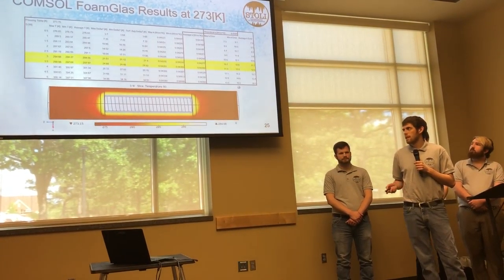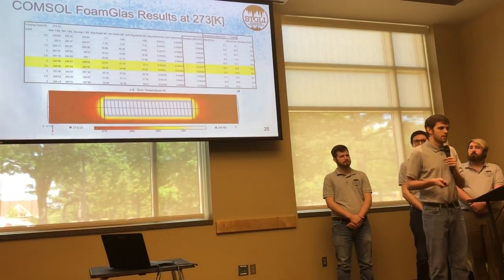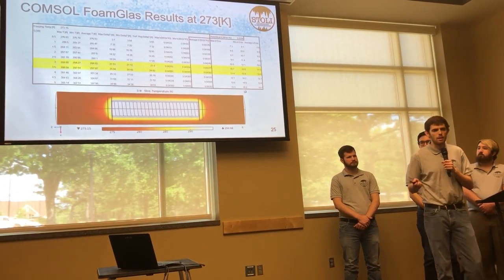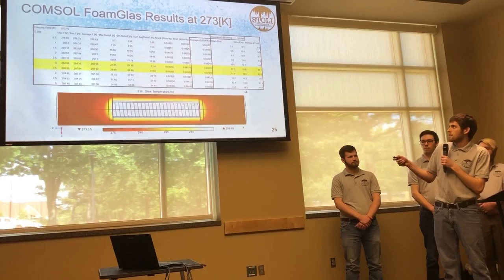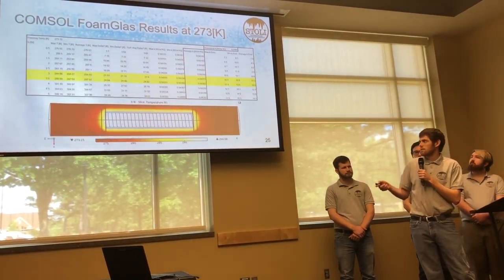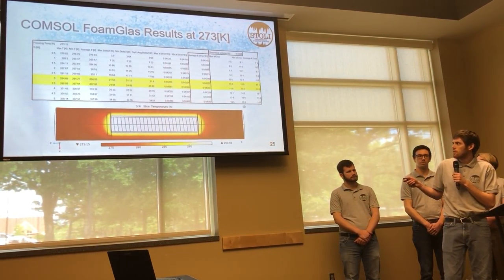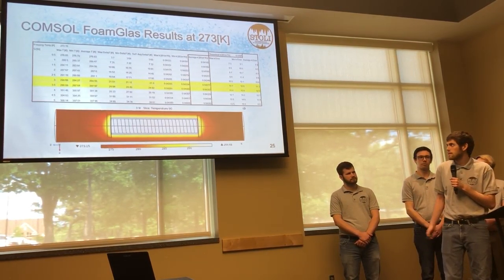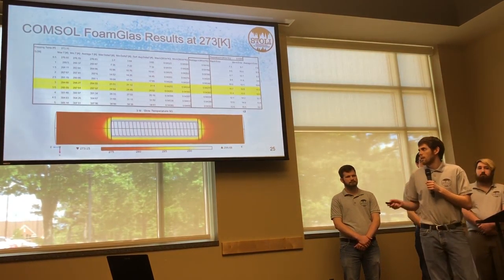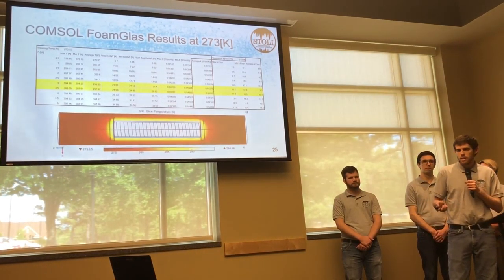Here is some COMSOL data. For our experimental tests we had a power input of about 3.25 watts. With our COMSOL results for foam glass at zero degrees Celsius, we found a thermal conductivity of about 0.042, whereas the rated thermal conductivity is 0.038. There is some heat loss in the axial direction. Next, Jed will talk about our experimental results.